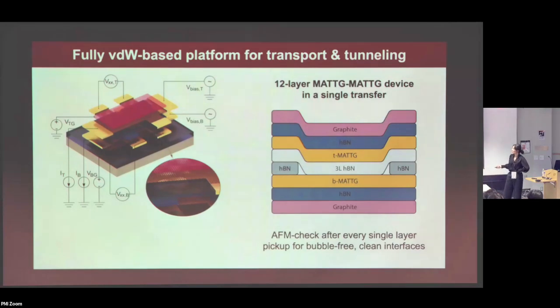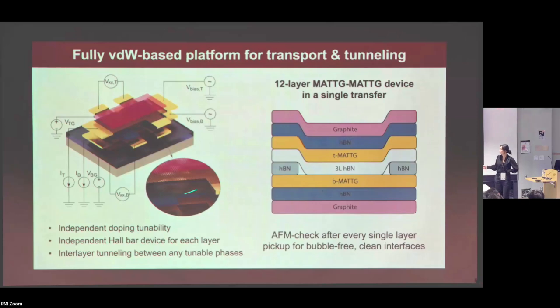With this kind of design, we can independently dope both top and bottom magic angle twisted trilayer graphene, and we can etch the entire device into the Hall bar shape and do full-blown Hall bar measurements. And exactly for the same region, we can do the interlayer tunneling spectroscopy across these two magic angle twisted trilayer graphene between the different phases that they have.